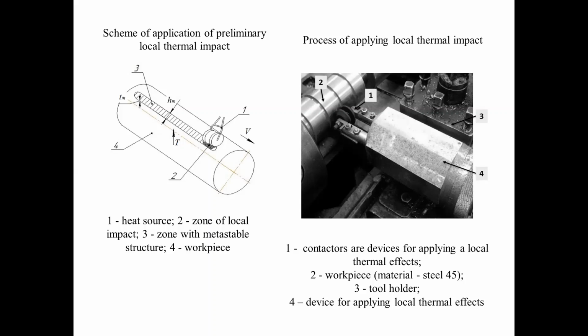The formed local metastable layer on the surface of the workpiece differs in its mechanical properties from the main part of the material, which, at the intersection with the cutting plane, will lead to an instant change in the stress-strain state in the chip formation zone, affecting the properties of the closed, potentially self-oscillating technological system, and thus dynamically stabilizing the machining process. The machining process must be dynamically stabilized in order to ensure the specified values of surface roughness and form accuracy. Let us consider the nature of the proposed local heat treatment method.